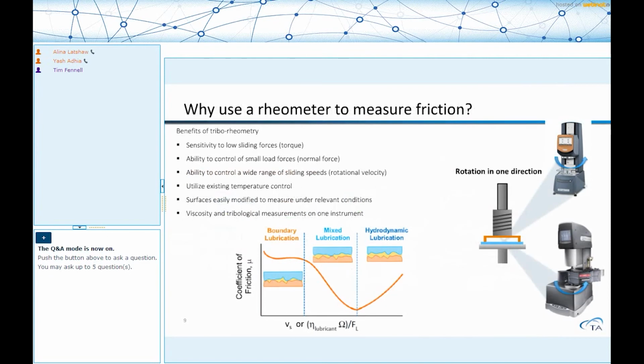So why do we use this rheometer to make friction measurements? First of all, because of the nature of the measurements we talked about in the previous slides, in general, a rheometer is very sensitive to low forces. So if you're trying to measure the frictional properties at low forces, or what we call torque, the rheometer is very well adept to make those measurements. While it can make rotation, or perform measurements along the shear direction, it can also make measurements in the normal direction. And it can also at the same time control the amount of force that you're applying in the normal direction. So you can press the materials by different extents and you can make these changes in very small amounts much more adeptly than any other instrument that is out there.